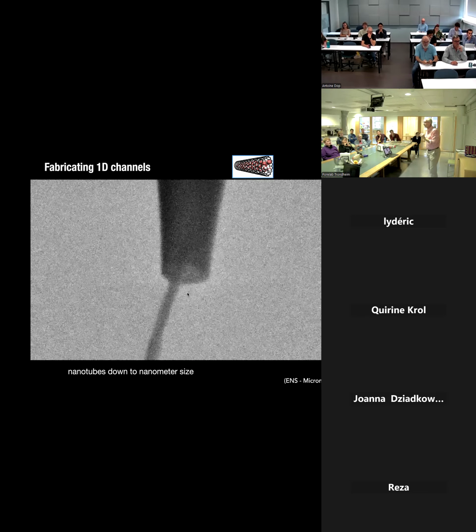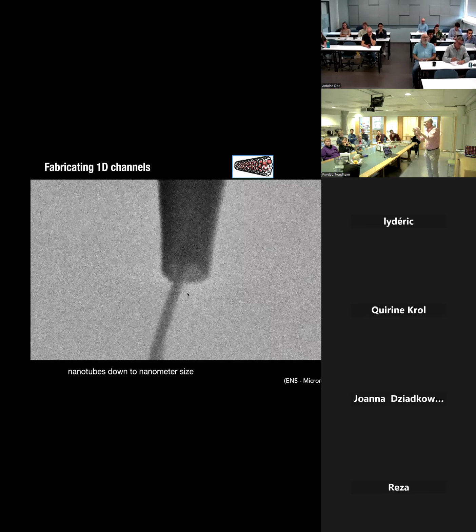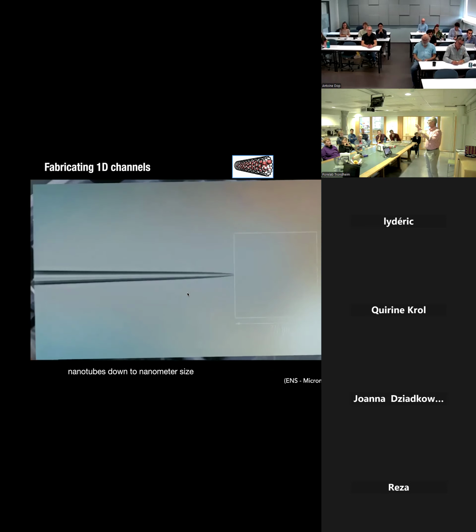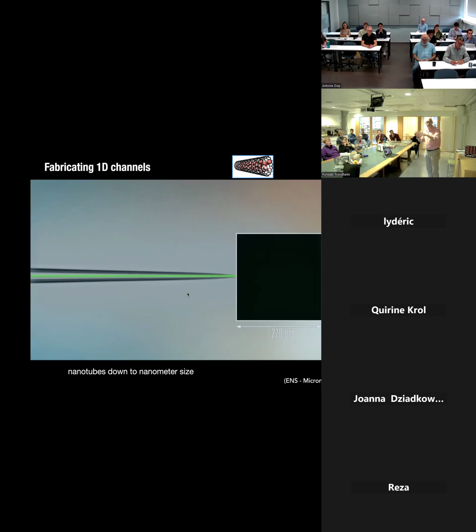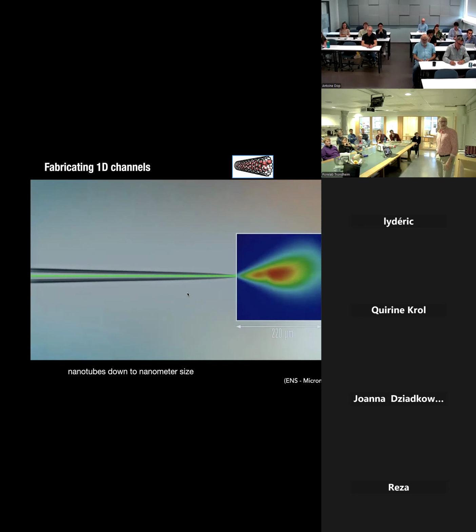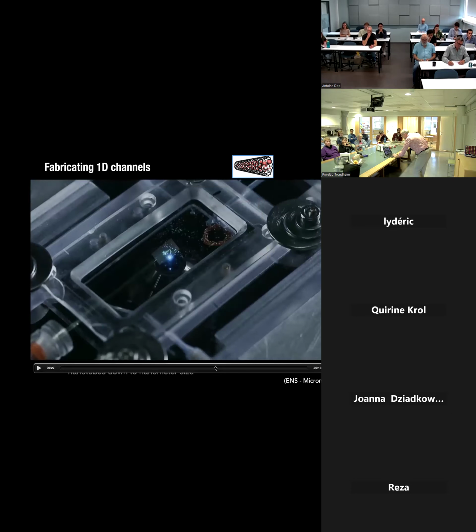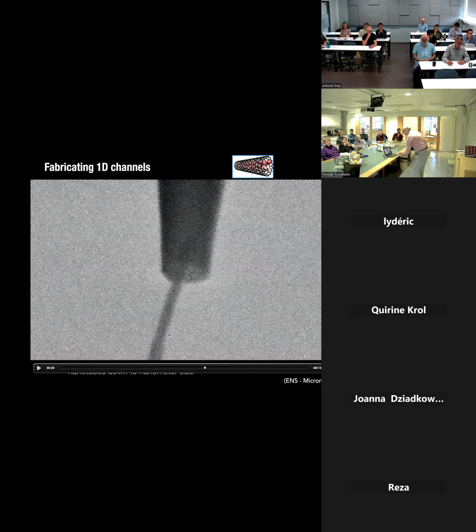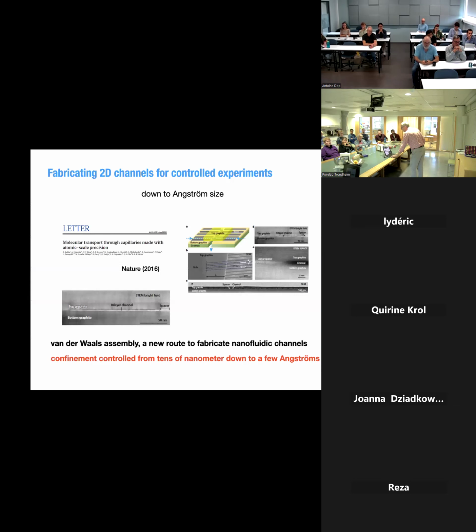And you can glue it with an electron beam and you crack a gas there. And this you can do by inserting it in nanopores, but you can also insert it at the end of a nanopipette, like that. And at the end, once you have, for example, here a nanotube inserted at the end of a nanopipette, you can seal it. And once you have that, you can really keep the pressure and start measuring things. So that's basically how we started doing a lot of things.